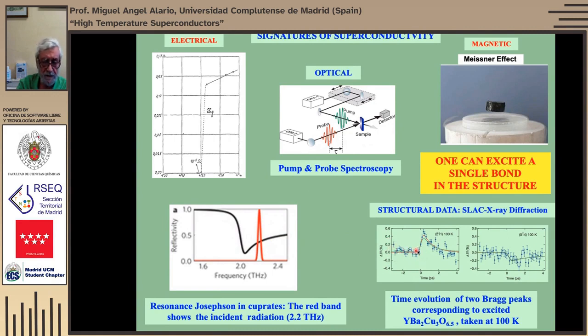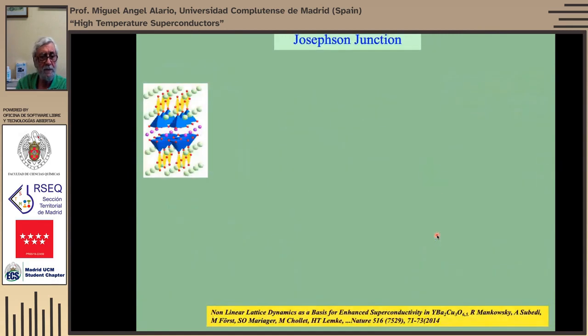Here we represent the variation of the intensity of the peak as a function of time. You see it increases, and then as the pulse disappears, it goes down. And they're in different X-ray lines. So two things you have to do. On the one hand, spectroscopy, and on the other hand, structural data in a very, very short time. So this is very difficult to do, but it has been done.